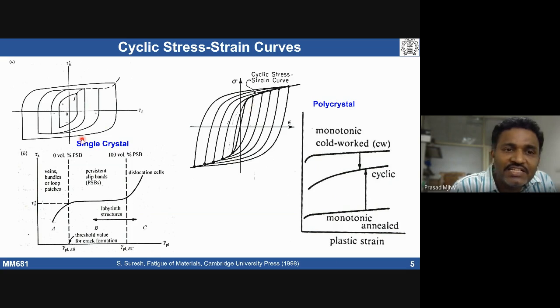In case of a single crystal, typically we get this kind of loops. There are no grain boundaries, so we don't see much strain hardening initially. We see almost constant stress for some length of time, where whatever dislocations have been generated get realigned. That can lead to formation of persistent slip bands. Then after a certain amount of further deformation, the bands lead to additional dislocation generation, which can lead to a dislocation cell structure.